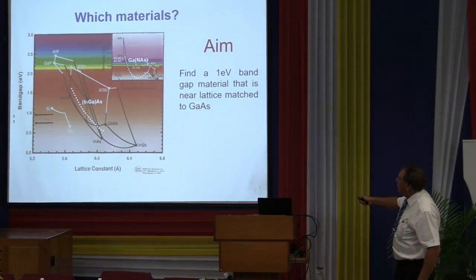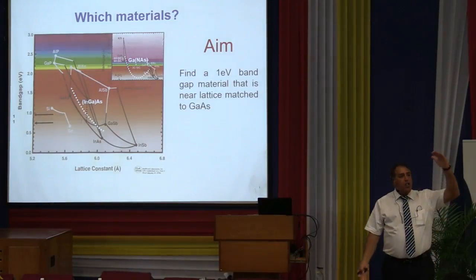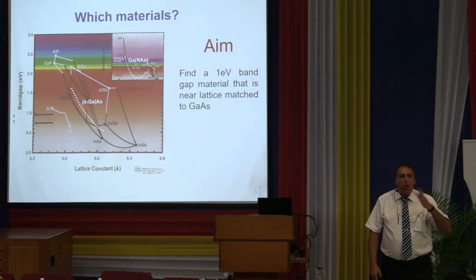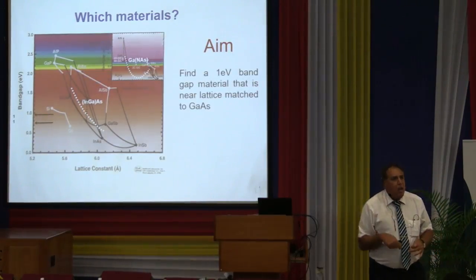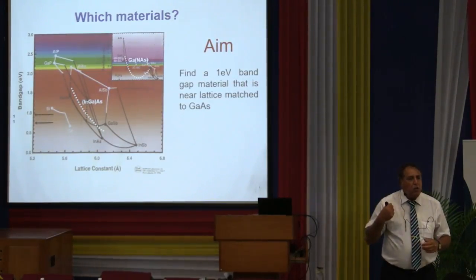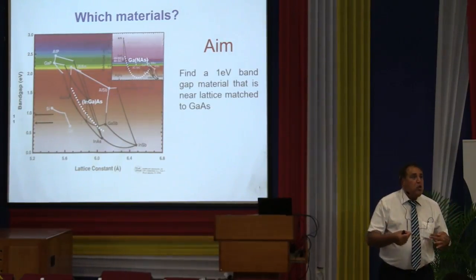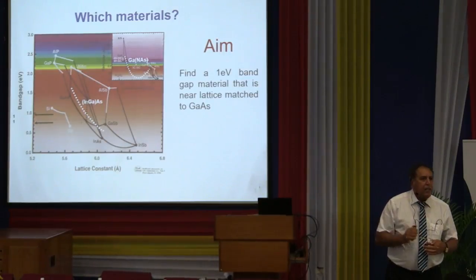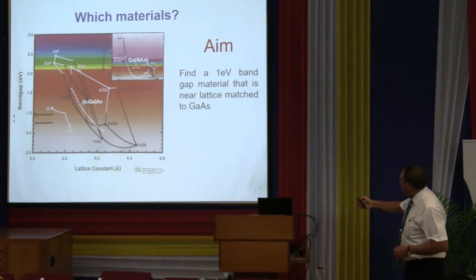So here's gallium arsenide, and here's gallium nitride. I hope I can explain it as simply as I can. Gallium nitride has got a large gap, so this produces blue. If you've heard about the Blu-ray disc, they use this material system because it produces blue light. And we know we can actually produce blue lasers which emit light in blue. But what the people found is that if you add nitrogen to this gallium arsenide, it doesn't go this way.